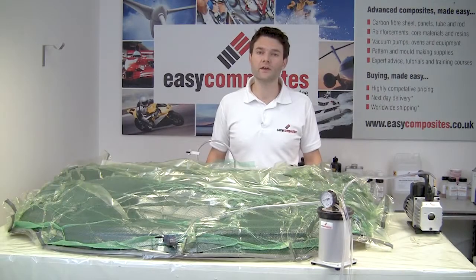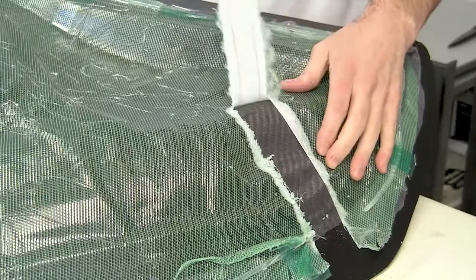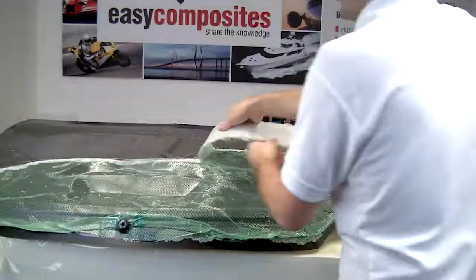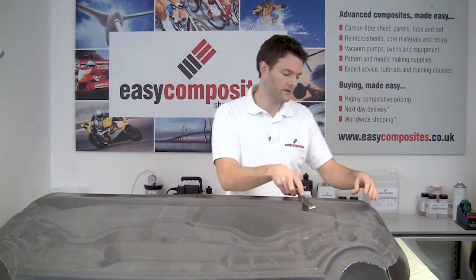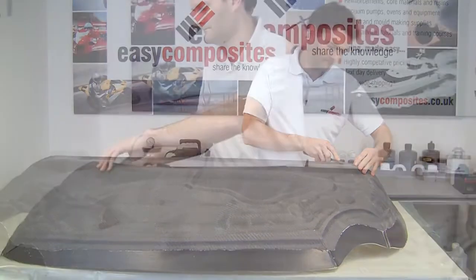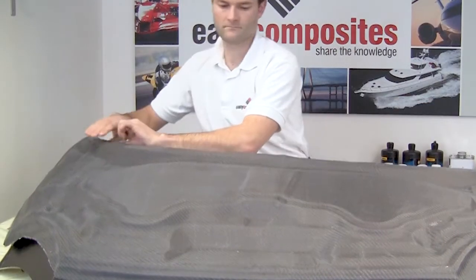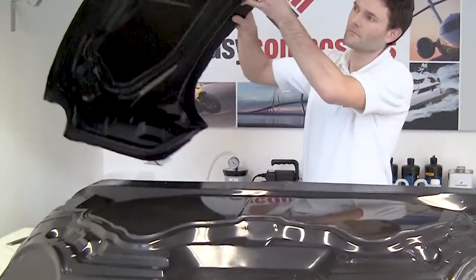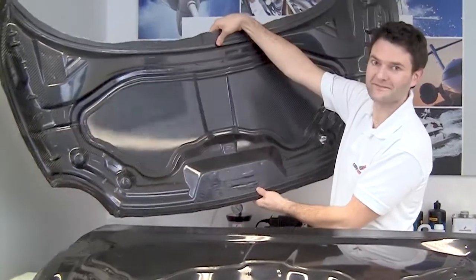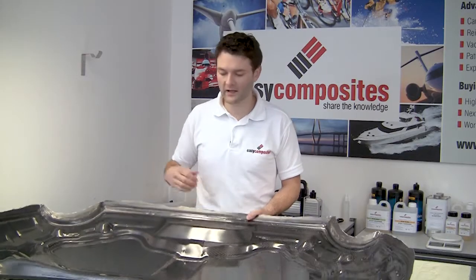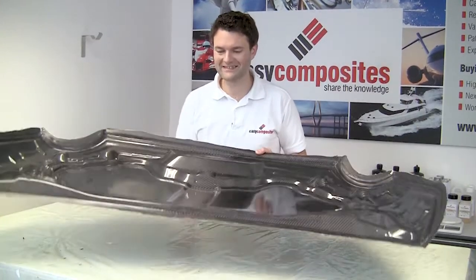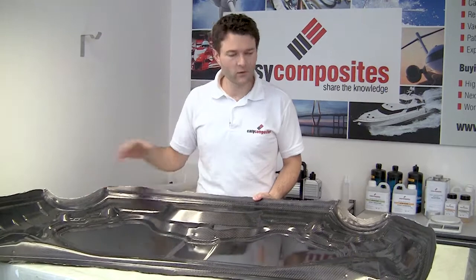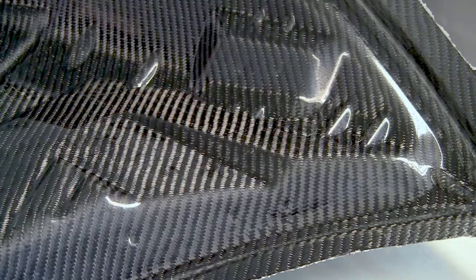We've now left this part to fully cure, and so it's time to strip off all of the vacuum bagging consumables just like normal. With everything stripped off now, we'll just remove the part from the mould. And that is our inner moulding. Now that we've got the mould out of the way, we can have a nice look at this part itself. It really is incredibly strong and light, and all of the detail that we've got on the underside moulding, of course, has been faithfully reproduced in this inner skin. So this is going to make a fantastic inside for our bonnet.